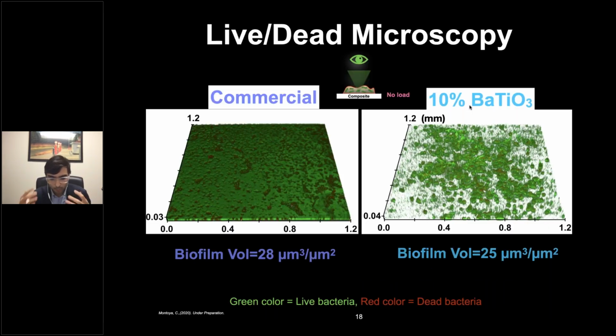Then we went to the microscope to see visually what's going on at the surface of the material. The green shows live bacteria, the red shows dead bacteria. In a 1.2 by 1.2 millimeter space, you see a clear and determined biofilm formation, thick, around 30 microns, very evenly distributed. If we measure the biofilm volume, it's around 28 microns cubed.